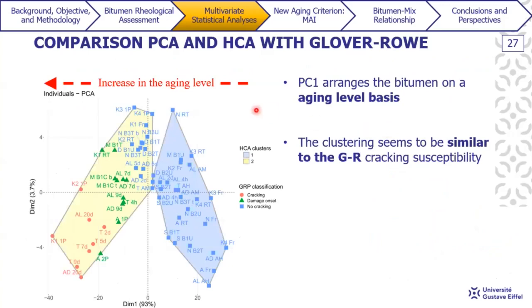So using this clustering analysis, we managed to cluster our bitumen into two clusters here. We have cluster one, the blue one, and cluster two, the yellow one. And in this example, just to facilitate the interpretation as well, I color code each individual using the Glover-Rowe parameter cracking classification here. The blue one represents bitumen that doesn't display increased cracking propensity. So they are all here in cluster one.